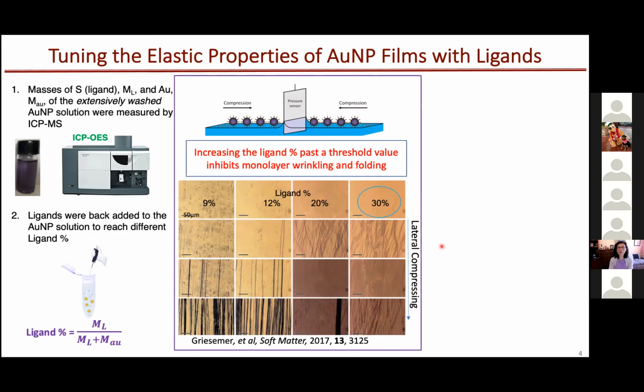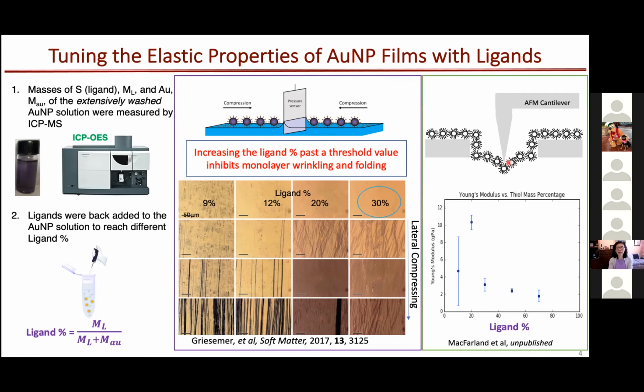When we measured the Young's modulus, we found it peaked at about 20% of ligand mass percentage, and beyond that point, the Young's modulus dropped quickly.